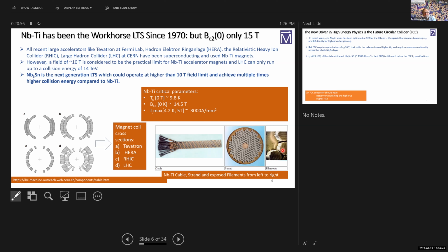And for a real accelerator, there are typically 1,000 to 2,000 filaments in each of these wires. What that means is you have a very good superconductor, which is stabilized somewhat against slight electromagnetic instabilities by the copper. So if there's any sudden movement of flux in the filaments here, then there's eddy current damping, and essentially it becomes an individual local perturbation, not a collective perturbation. So this is a technology that works very well.